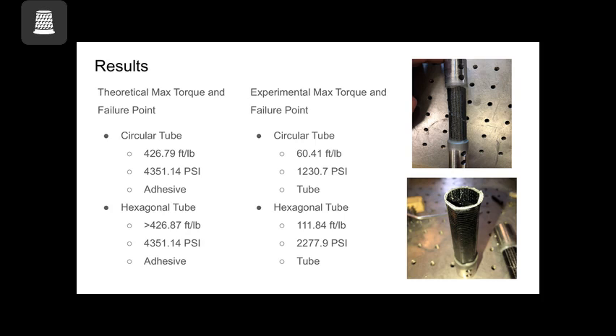When we look at our experimental max torque loads, we can see that the circular tube came out to 60 foot-pounds and about 1200 psi, but unfortunately these specimens broke at the tube most of the time, meaning that this was inconclusive data. Same for the hexagonal tube, an increased torque load of about 110 foot-pounds, coming out to 2200 psi on the adhesive bond, and these also broke at the tube.